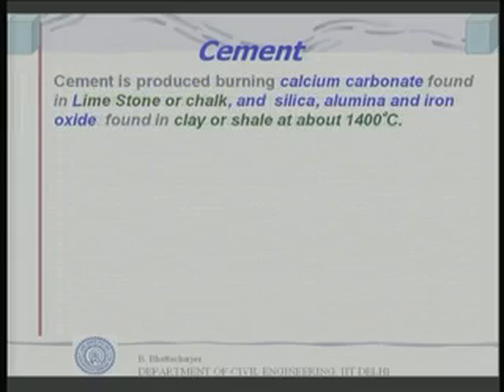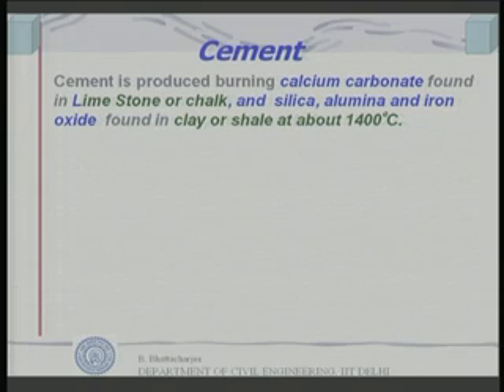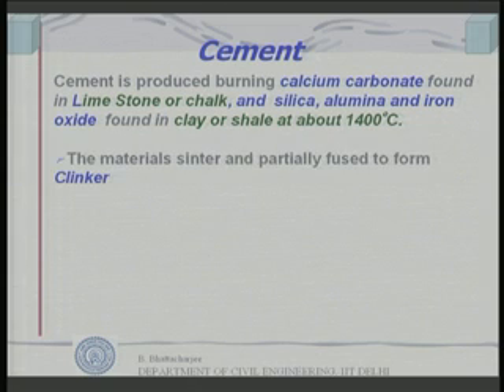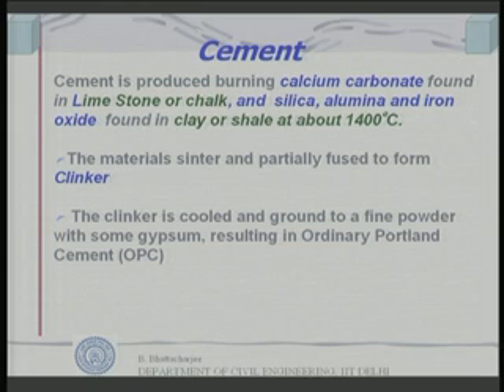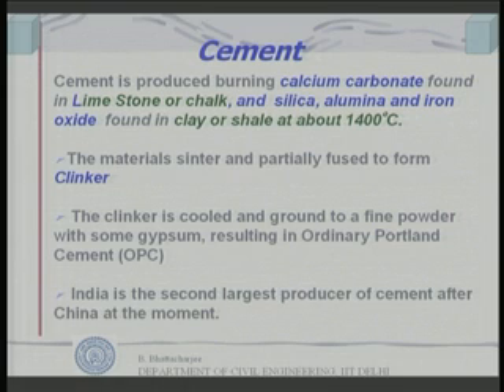Now, as we mentioned in the last module, cement is produced by burning calcium carbonate found in limestone or chalk, and silica, alumina and iron oxide found in clay or shale, at about 1400 degrees centigrade. So, we burn limestone with clay. This material sinters and partially fuses to form what is known as clinker. Clinker is cooled and ground to a fine powder, a little bit of gypsum is added in the process, and this results in what is known as ordinary Portland cement, OPC in short form.